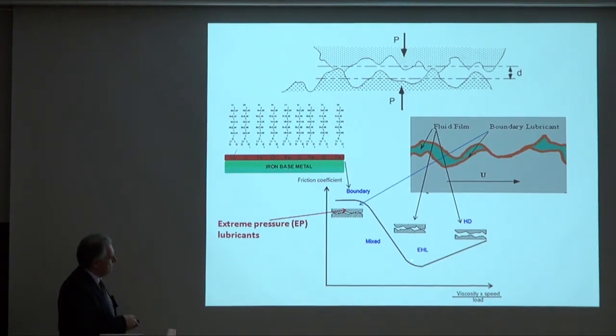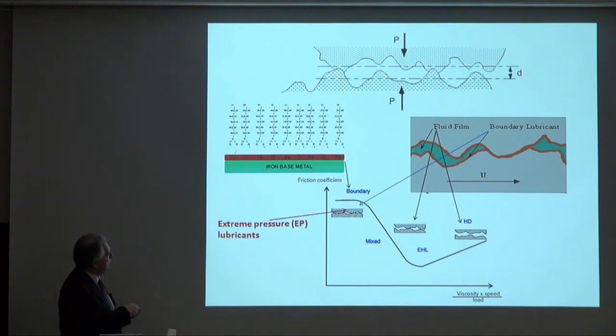Things start getting bad after this point, where we can see a sharp increase in the friction coefficient. And here we can see values that are 3 or 4 orders of magnitude higher than what we had in the previous regimes. This is because now we have squeezed out all this fluid. This green fluid that you see here has been completely squeezed out between these two surfaces. And we have a case like this.